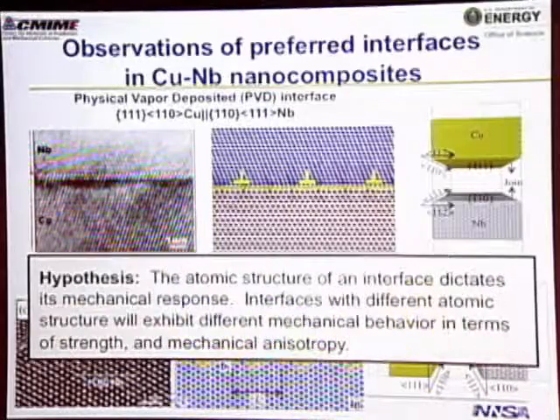If we look at the roll bonded interface, what we find is that we get something that's very, very different. So you can see here that this interface is serrated. It has these little ledges between the copper and the niobium. So instead of it being flat, now it's got these kind of teeth that lock it in place. And so in this case, the crystals are in the same orientation relationship. All we've done is instead of joining them like this, we're now joining them like this. And so we join them along their 1-1-2 planes in this case. So very different interfacial structures, and we're going to see that the properties that we measure are also very different.